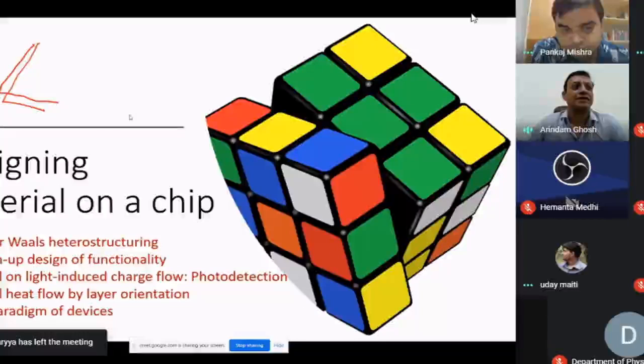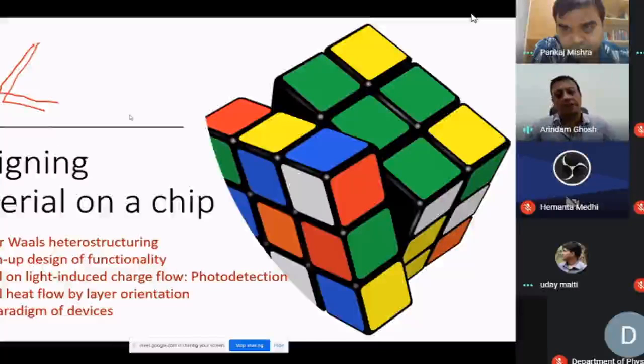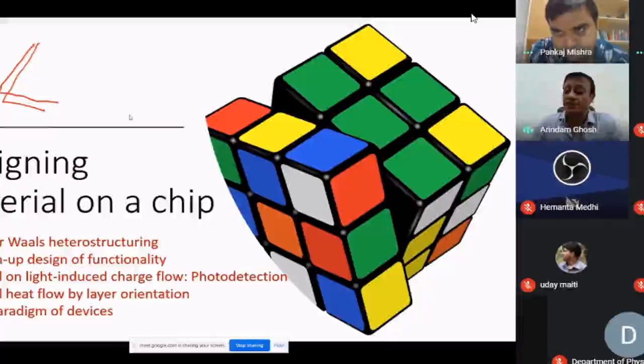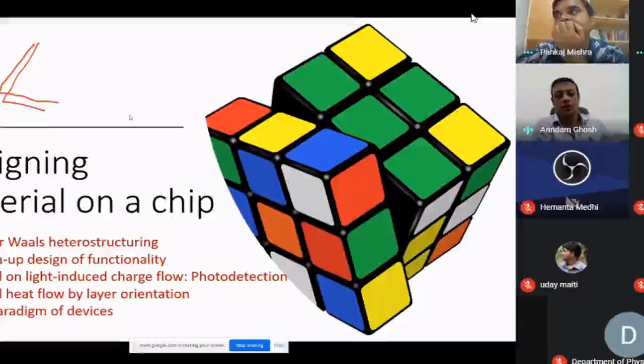Yes, so that's a very good question. In fact, these days, if you ask the students, they use a graphite gate instead of silicon oxide. So what happens is on silicon oxide, you put a graphite, which is like a really metallic system. And normally, most of these traps come from silicon oxide, as you correctly said. Although, that said, we have recently published a paper, Saloni and others did very nice, interesting work, in which we showed that our residual scattering is coming from the lattice defects in boron nitride, which is really surprising. Boron nitride is supposed to be, and we get boron nitride from Japan, one of the best quality boron nitride that is available on Earth. And even then, the scattering is now no longer from those in the silicon oxide, but the defects in boron nitride actually can end up scattering. Okay, so we have to find ways in which we can, if we can.